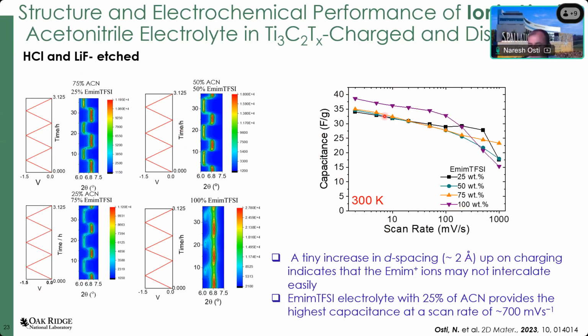But if you look at the electrochemical performance as a function of the scan rate, at low scan rate, you don't see that much difference as a function of the acetonitrile concentration. But if you look at the higher scan rate, somewhere around 700 millivolt per second, you see the capacitance is higher once you have that 25% of acetonitrile in the system. That's what we found here.